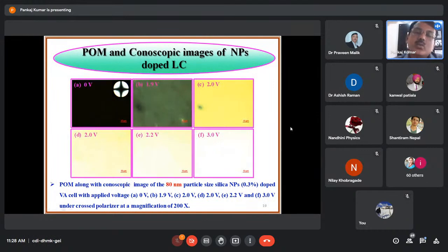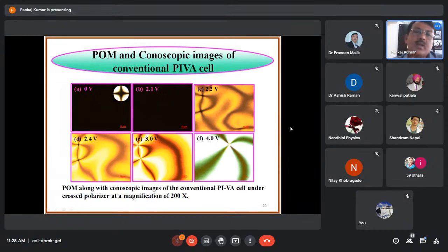In figure B, you can see 1.9 volt, 2.0 volt, 2.2 volt, 3.0 volt. So the 80 nanometer as well as the 15 nanometer are giving a very good dark state as well as a very good bright state. And this figure is the